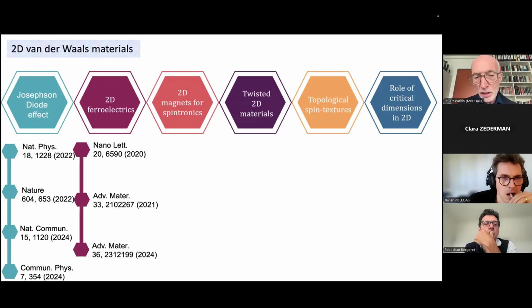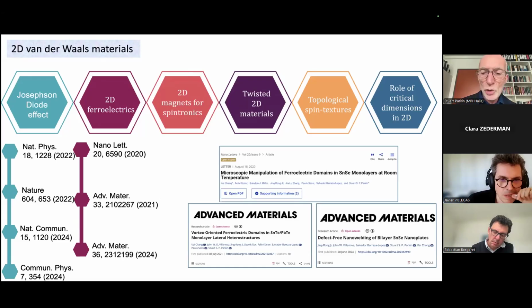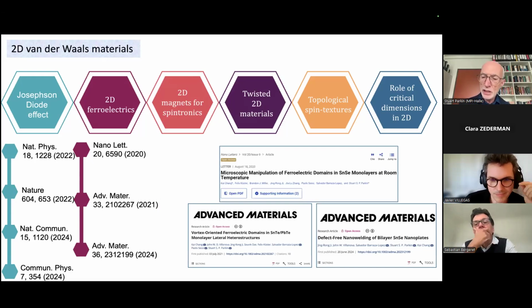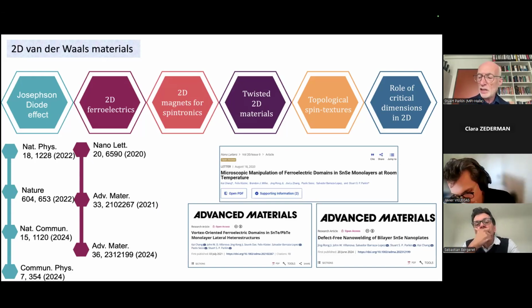So unrelated really, we're also very interested in 2D ferroelectrics. And the polarization of these materials turns out to be very interesting in these 2D materials. We actually grow most of these materials not by exfoliation, but by molecular beam epitaxy techniques. And what we were able to show was that we could form extraordinary ferroelectric materials in, let's say, monolayers of tin selenide. And they have an ordering temperature for the ferroelectric polarization several times higher than the bulk material. And similarly for tin telluride.